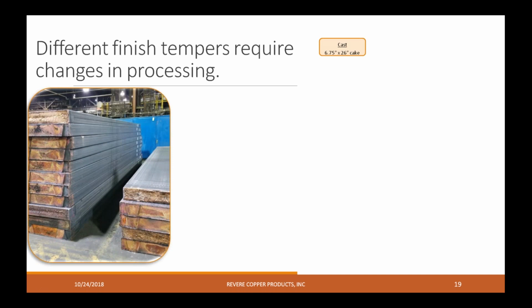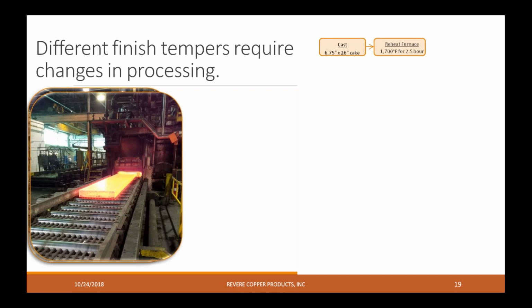So I'm going to put that all together for you, a lot of information to process, into basically what you do when we're rolling metal. So we cast these cakes. They're also called ingots in the market, and they are 6 3/4 inches thick, and they're black on the outside. That's an oxide that forms, and that has to do with the copper being highly reactive, and it's heated to 1700 degrees for 2.5 hours. So this particular cake was 6 3/4 inches thick, 26 inches wide, and 25 feet long.